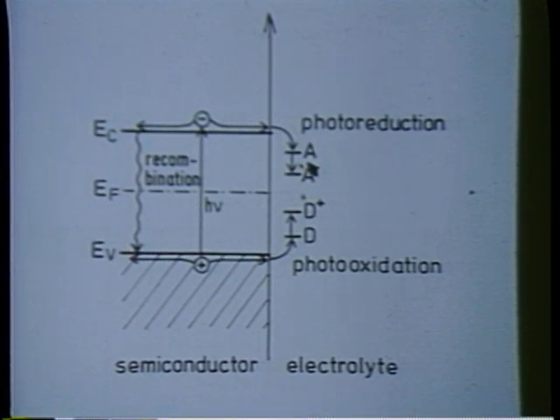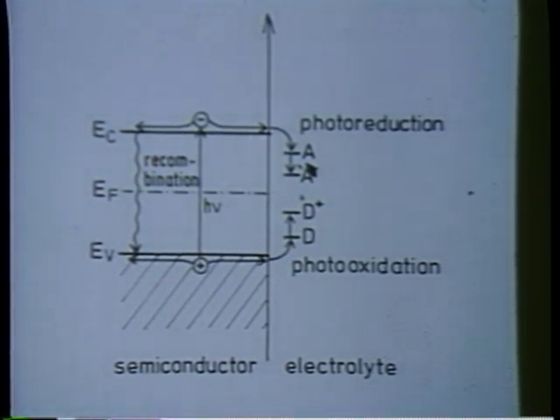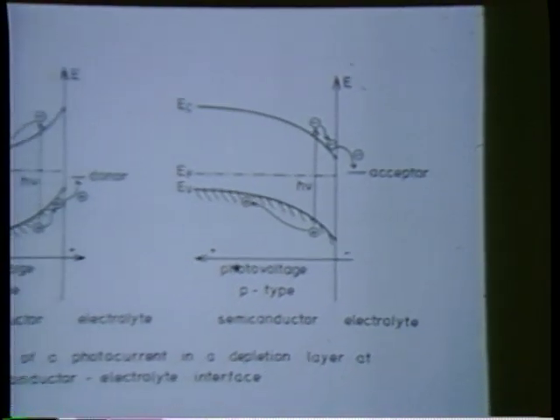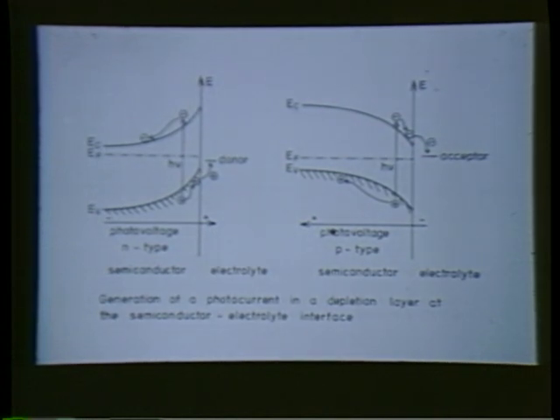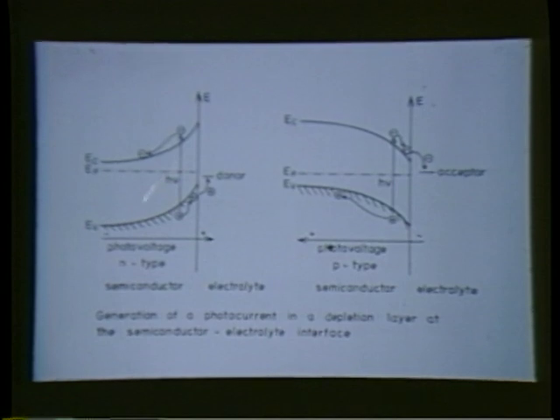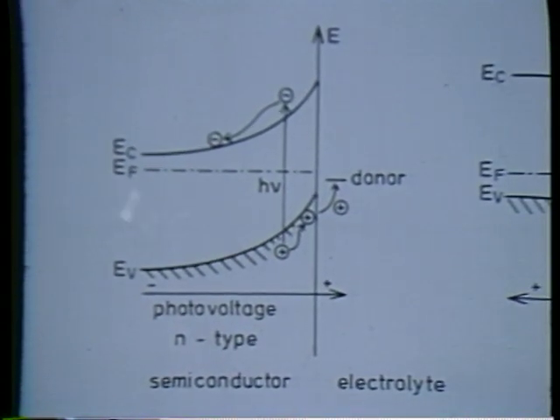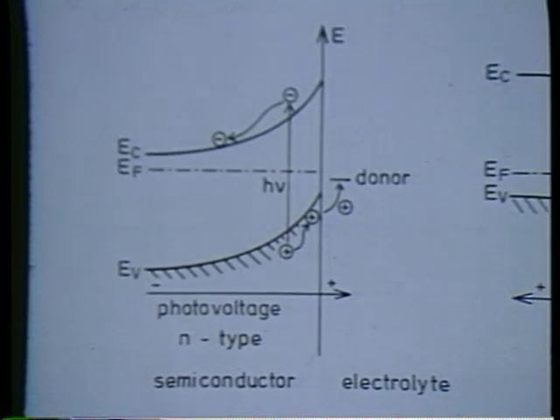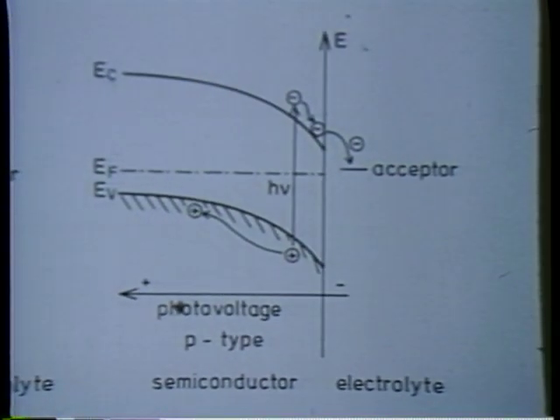Now we can separate these processes in a very simple way just by applying a bias. If we apply a positive bias, then we draw the electrons to the bulk and push the holes to the surface, and vice versa. And in this way, photocurrents can be generated. And again, the photocurrents are generated particularly under the situation of depletion of the surface, because only in this case we have this high field at the surface which separates electron-hole pairs. And here is a situation for photooxidation by holes in an n-type material, and here is a situation for photoreduction by electrons in a p-type material.